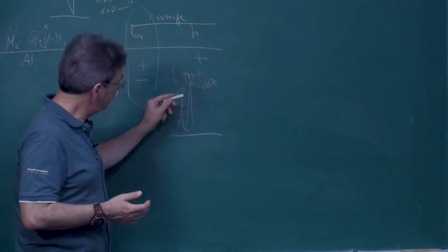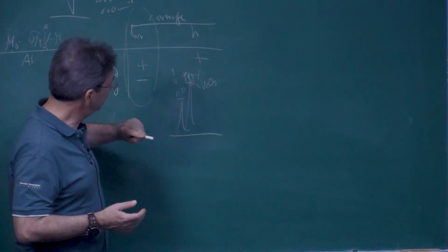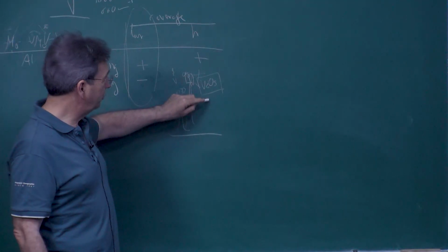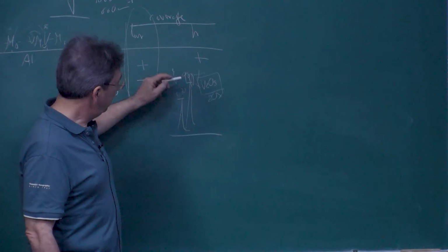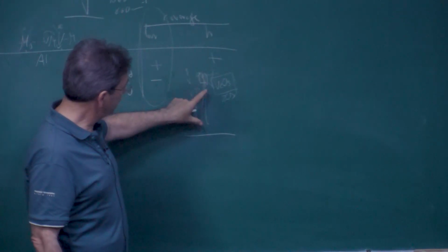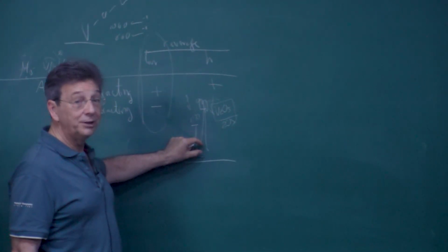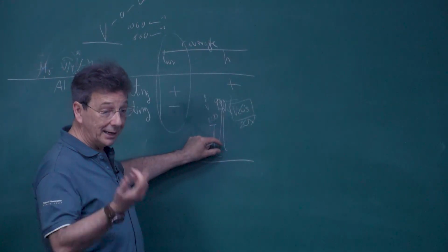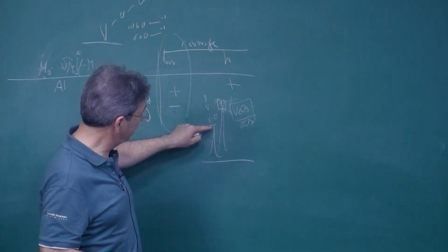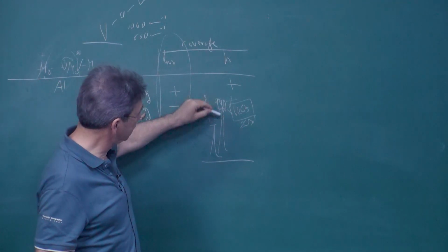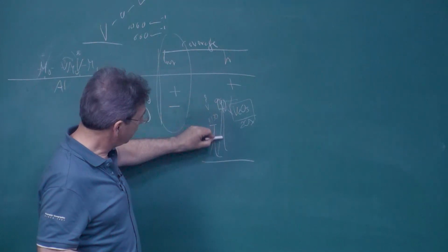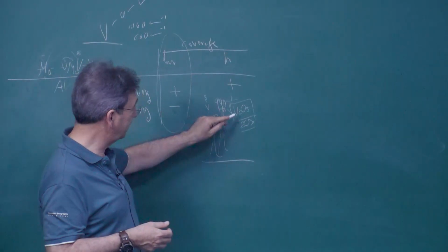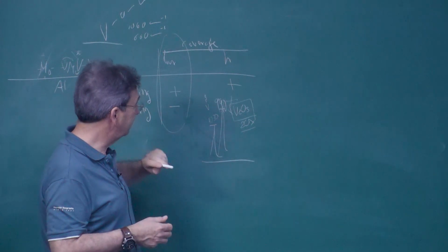Now, even when this band is stronger than this one, the Raman cross section of the crystallites is very high. It was calculated to be about 20 times higher. So even when you get this signal, the reality corresponds to something 20 times smaller, which tells you that Raman is extremely sensitive even to nanocrystallites. And also, when you see that this band is stronger than that one, that doesn't mean that you have many more crystals than dispersed vanadium, because the Raman cross section of crystallites is about 20 times stronger than that of dispersed vanadium.